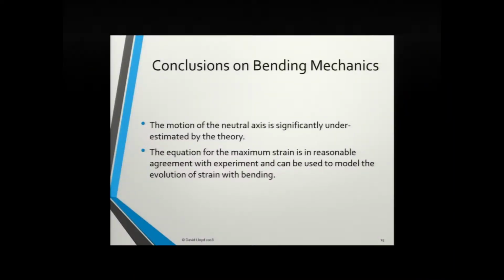The motion of the neutral axis is significantly underestimated by the theory, and that's important under certain circumstances. For what we're talking about today and going on, it isn't, but it is important to bear this in mind if you want to compare damage models and so on. And it's important if you're looking at graded structures. In other words, if you're looking at variation in grain size through the thickness, or a variation in particle content through the thickness, or you're looking at sandwich panels, it's important to appreciate where that neutral axis is and where it's going as you're bending it. Because the damage essentially is progressing quite significantly deeper and deeper into the sample.